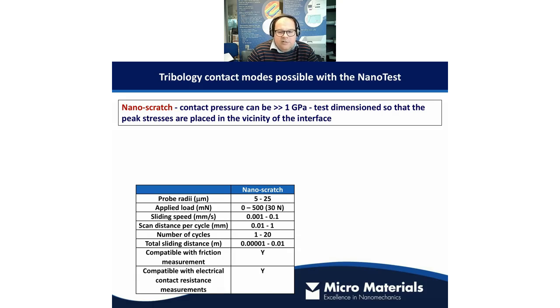So often what people are interested in there, often what happens in a tribological system is you get a detachment of a coating material from a substrate. So that's to say that the coating itself doesn't necessarily fail, and neither does the substrate, but the interface does. So that's one of the major things that scratch testing is interested in.